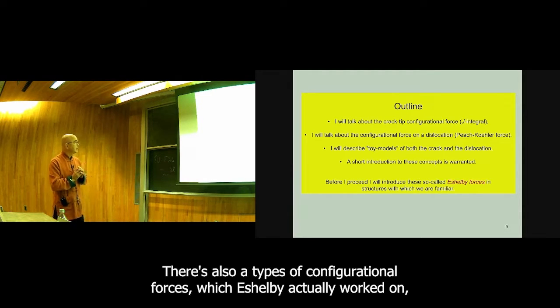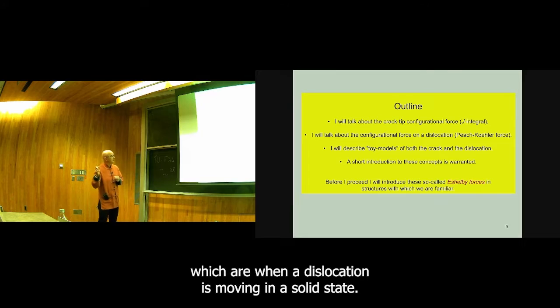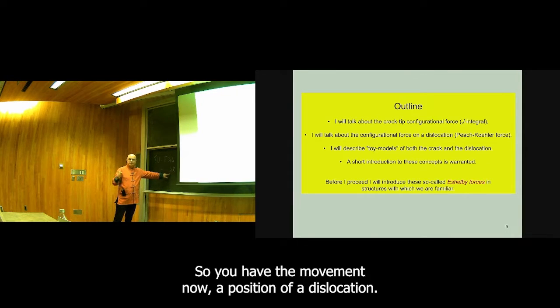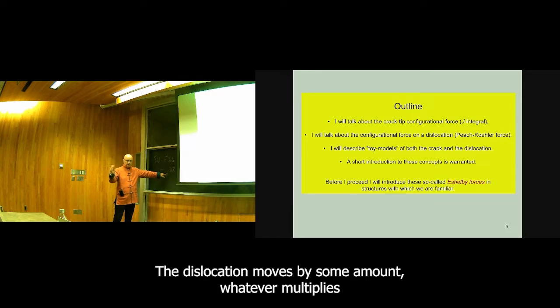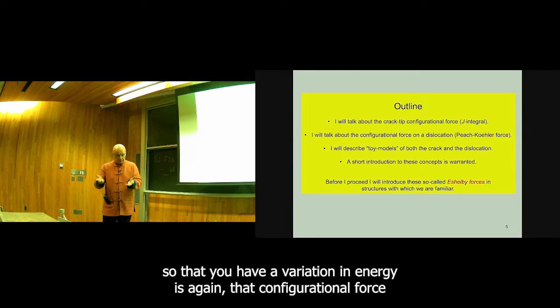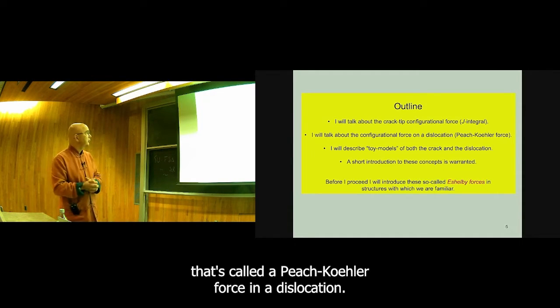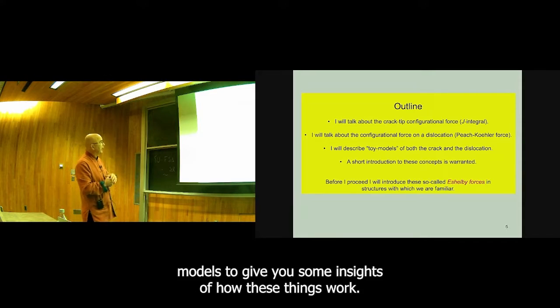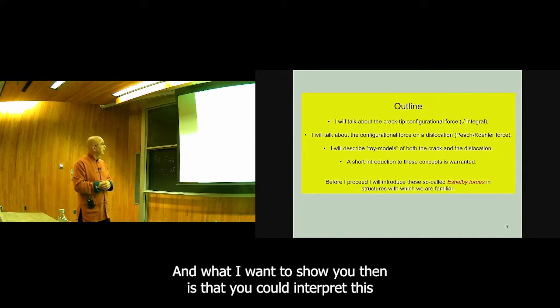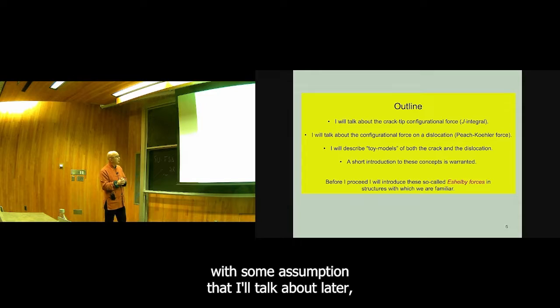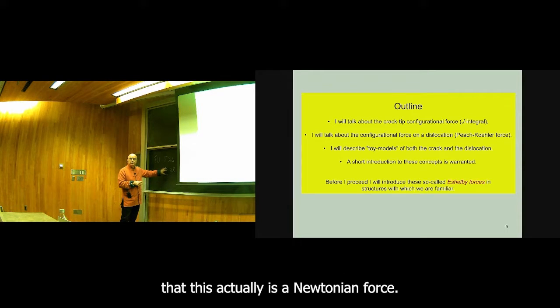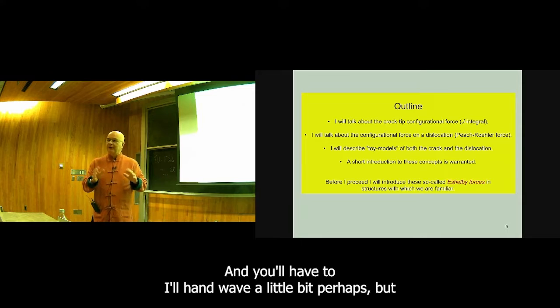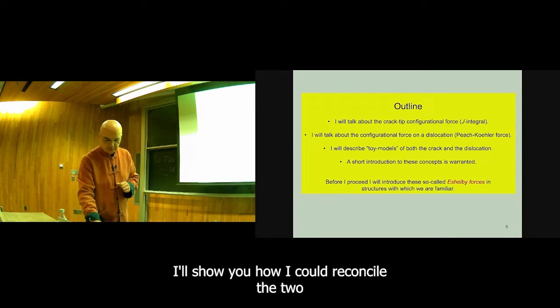There are also types of configurational forces which Eshelby actually worked on, which are when a dislocation is moving in a solid state. So you have the movement now, the position of a dislocation, the dislocation moves by some amount, and you have a variation in energy, which is, again, that configurational force. That's called a Peach-Koehler force in a dislocation. I'll start out with some toy models to give you some insights of how these things work. And what I want to show you then is that you could interpret this, with some assumption that I'll talk about later, as actually a Newtonian force. Okay? And I'll hand wave a little bit perhaps, but I'll show you how I could reconcile the two.